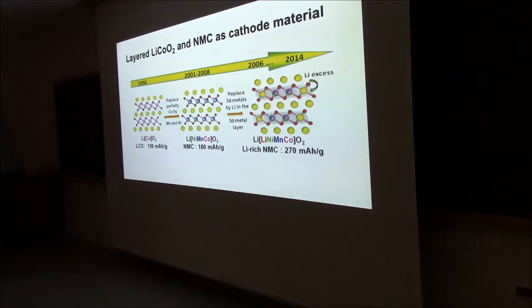We call these lithium-rich materials, and this increased the energy density dramatically. Those are the materials that you use nowadays. And you can see in here, it's the nickel, manganese, cobalt. They call this the NMC. If you look for batteries, they really like these abbreviations, so you will find batteries are NMC batteries, I think that, and it's this material.